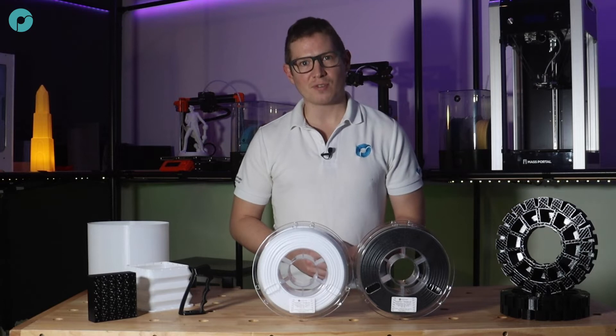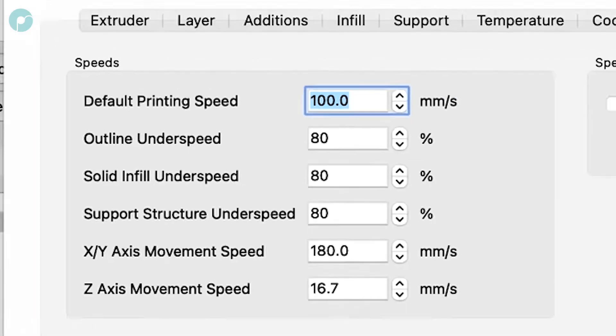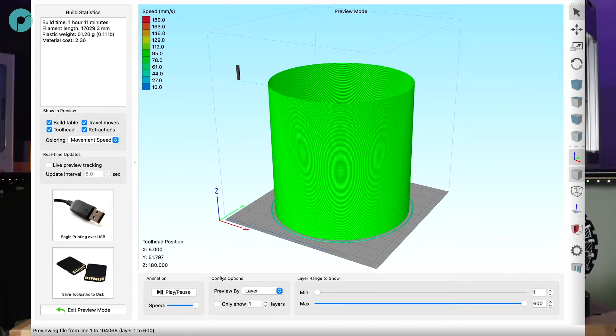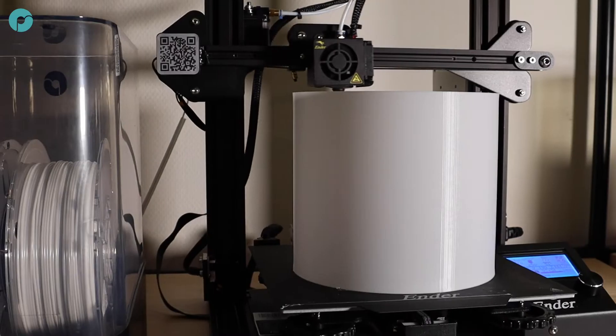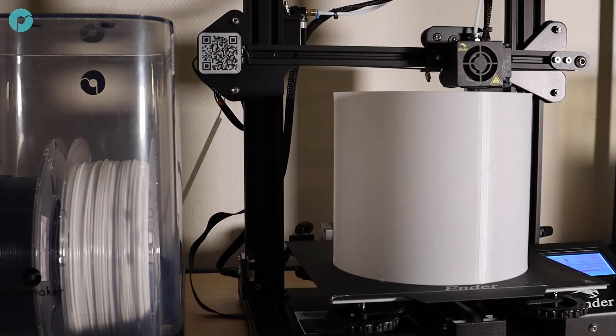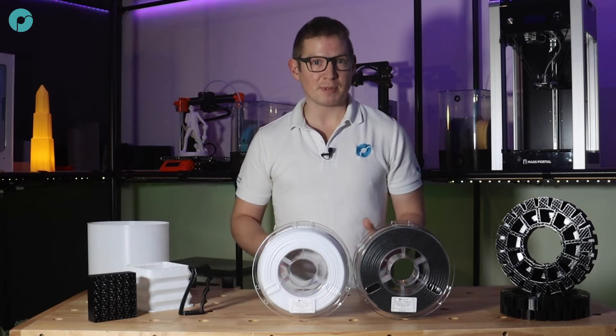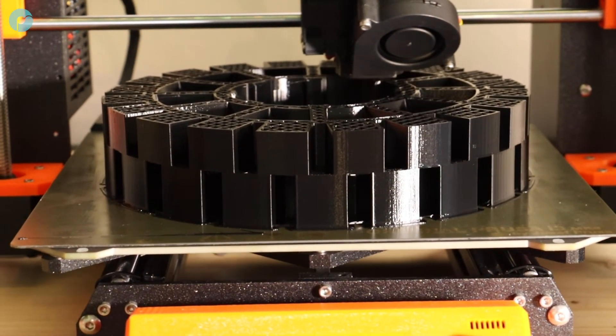To test the limits of the filament I wanted to try a print at 100 millimetres per second, and to make it even harder I printed it on an Ender 3 with indirect drive. I was honestly blown away by the feed rate and consistency — 100 millimetres per second is crazy fast for a flexible filament, even compared to a more modest 60 millimetres per second which is towards the high end for printing PLA.